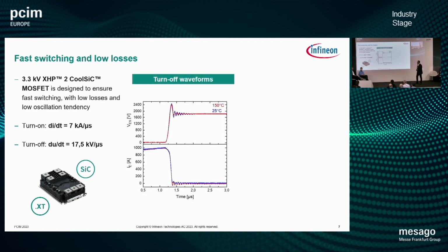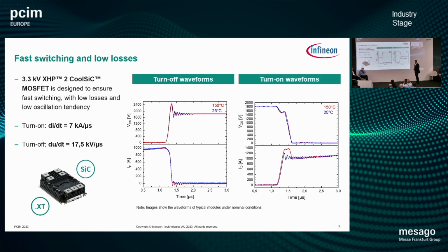And what you clearly see is that because we have a low inductive housing, the switching transients are almost negligible or very low compared to if the design is put into a high inductive module. The same is true for the turn-off behavior. We see absolutely no temperature dependency on the turn-off losses. This is in the range of around 180 millijoules for 1000 amperes, and around 450 millijoules for the turn-on energy.